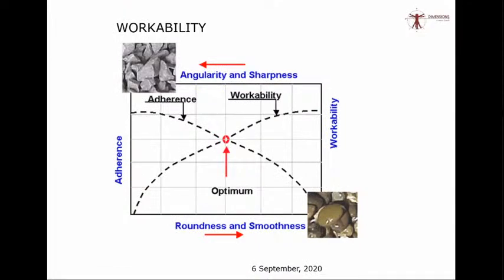Workability of concrete, I was just talking about the influence of the aggregates on the workability of concrete. In this picture, you can see two diametrically opposite forms of coarse aggregate. One is sharp and angular. The other one is rounded and smooth. Common sense would tell you that if it is round and smooth, you will get more workability. But then what will happen is you will not have enough adherence. You will not have enough bonding between particle to particle. So you cannot completely use smooth aggregates. You cannot use the pebbles completely as aggregates unless you have modified your mix proportion to suit that.